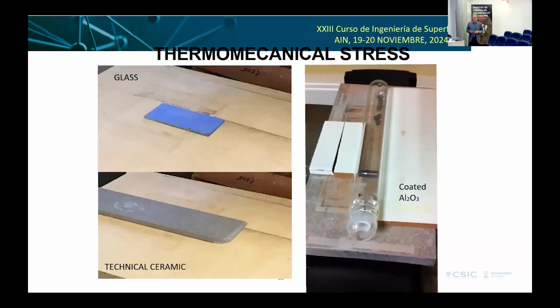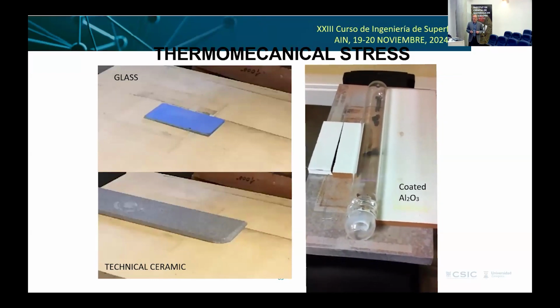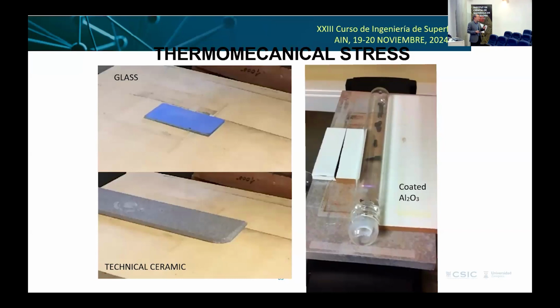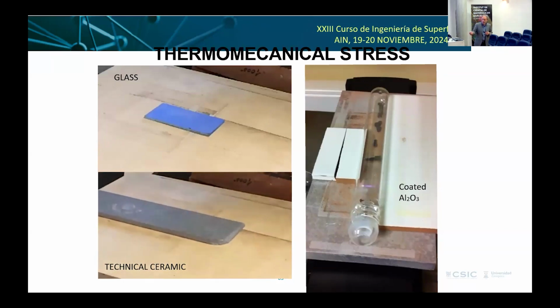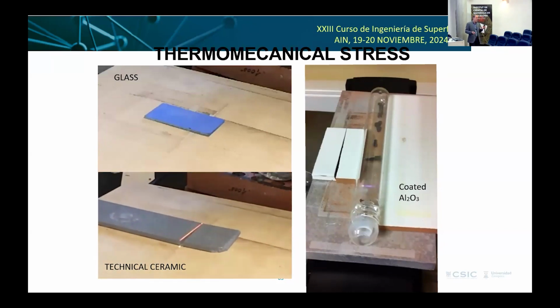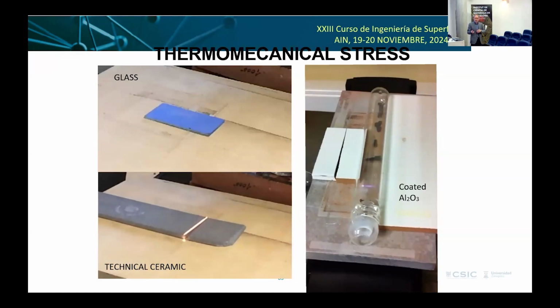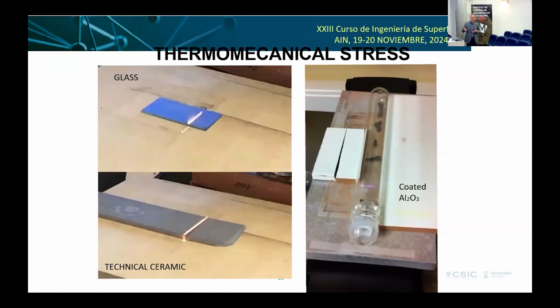We can see what happens here. This is a single crystal of alumina, random, with a metal layer. This is accumulation of heat. So this is what we don't want. We try to avoid it. But in this case, we want to melt. Now it's ceramic. We try to cut it, but we can cut it very nicely by the thermomechanical stress we induce with the laser, and also with glass, the same thing happens. So this means that materials which are not metals, which are not good heat conductors, always have a problem.